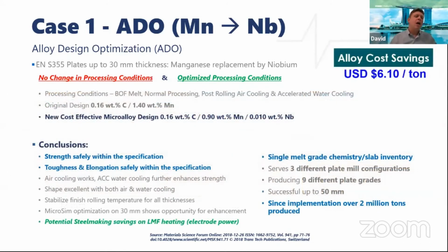And the conclusion is that, on top of achieving safely the mechanical properties of strength, ductility, and toughness, the material had a much lower alloy cost. We did have a little bit of extra cost in the steelmaking process that I'll show later on. And there was also some cost that we could not calculate, somehow intangible for us considering the information we had, related to slab inventory and process yield, because we had one single chemical composition that could make plates for three different plate mill configurations, because this company had three different plate mills.